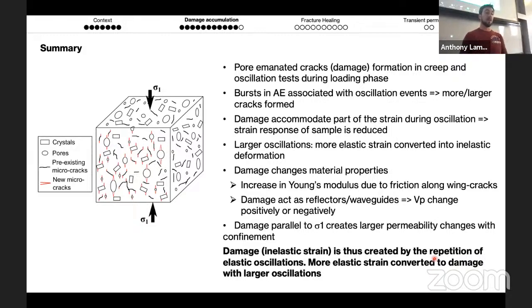And what's important is that those elastic oscillations, elastic deformation, should always come back: if you remove that elastic strain, it should come back to its original position. Here, what it shows is that if you repeat low amplitude elastic oscillations, you will end up generating inelastic damage, so not recoverable strain, into materials, and therefore you're going to fatigue this material over time.